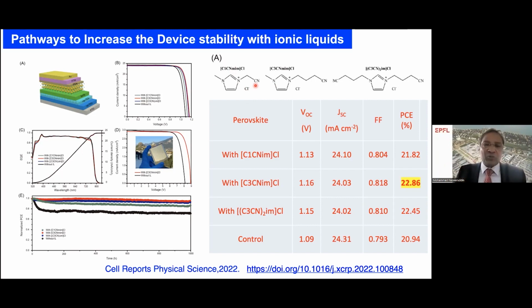of this perovskite composition. For that purpose, here we have taken 3 examples: one with a shorter chain containing a cyanide group, one with a longer chain with a cyanide group, and another with 2 cyanide groups with longer chains. Based on this data, the best one is the longer chain with 1 cyanide donor group, that's a coordinating ligand, which gives close to 23% efficiency. If you want more details, this is a recent publication. Now the configuration is the same, NIP, and we have even mini modules, which go over 21% efficiency.